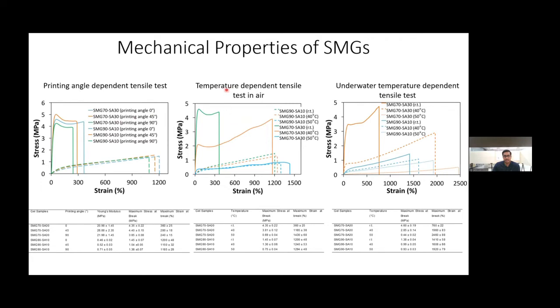And we have found interesting data for the temperature dependent tensile test method, and we have found that this dotted line represents SMG 90 SA10, where the amorphous concentration is higher. There is no significant change. And for SMG 70 SA30, where the crystalline concentration is higher, we have found that with increasing temperature from room temperature to 50 degrees Celsius, there is a significant change in the flexibility. And we also have examined the tensile test in underwater condition, and we have found with increasing the temperature from room temperature to 50 degrees Celsius, for SMG 70 SA30, the flexibility changes a lot.